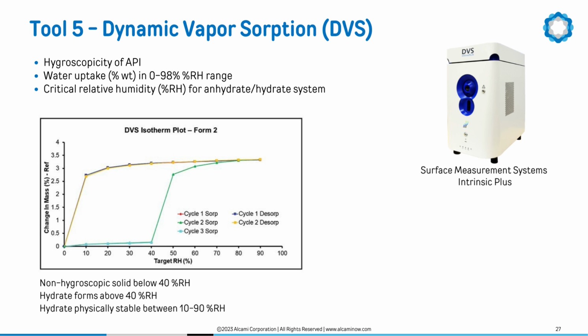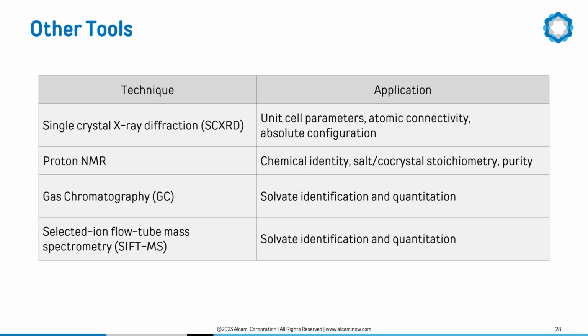Hydrates have significant implication in pharmaceutical development as they may affect solubility, they may become amorphous upon drying, or impact formulation strategies. Therefore, it is important to assess hygroscopicity and the tendency to form a hydrate for APIs in early development. Other tools applicable to solid-state characterization include single crystal X-ray diffraction, which can establish atomic connectivity in molecule and describe how molecules pack in the three-dimensional crystal structure. Therefore, this technique is regarded as a definite evidence of polymorphism. This technique can also verify absolute configuration of chiral centers in optically active compounds.